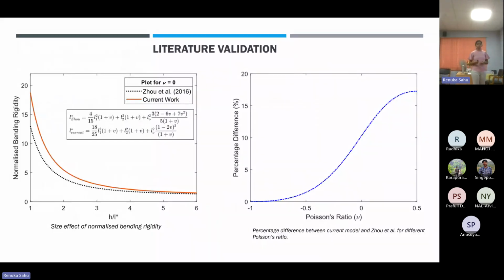We did the literature validation of our work with Zhou et al. We analyzed the variation of normalized bending rigidity, which is the bending rigidity with respect to classical bending rigidity, plotted against the H by L star ratio, where L star is defined here since that formulation was used in the literature. We move forward with that, and this is for the zero Poisson's ratio case.